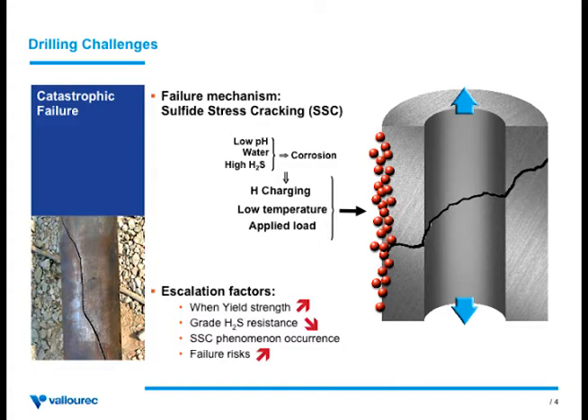Of course, drill pipe are being used in a mud environment, so it's a controlled environment. There is no reason why you would have H2S, acid, low pH, because usually the mud has a pH above 7. So the only condition that would be very unfavorable would be if you lose control of your well. If there is a kick, if there are fluids entering the annulus, if you drill underbalance, if you use MPD, then yes, there could be all those factors together, and then the mechanism will start.